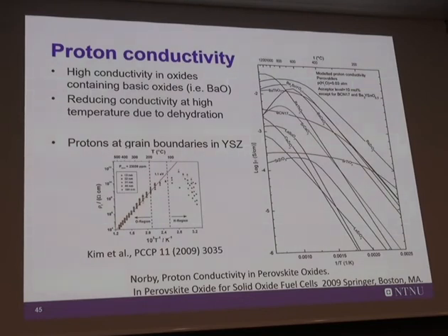The best one is barium zirconate, which, if you look at PZT and so on, is quite a similar type of material as we know in the ferroelectric region. And the conductivity can become quite high, so up around 500-600 degrees, you get quite reasonable proton conductivity.